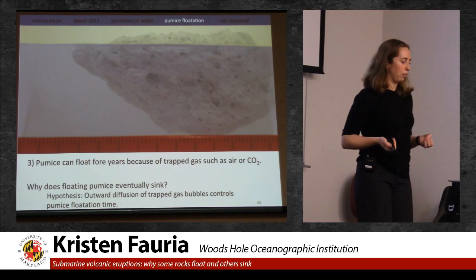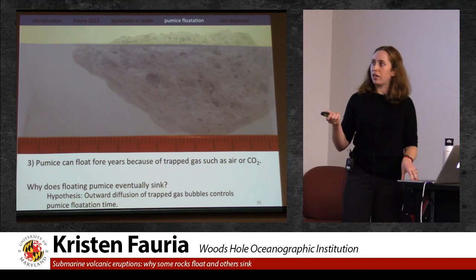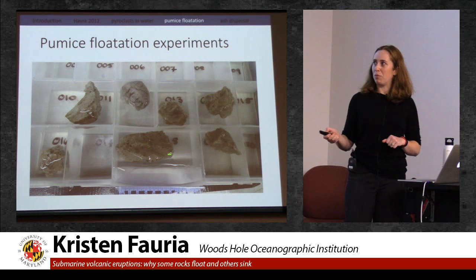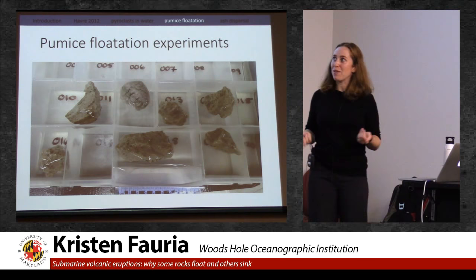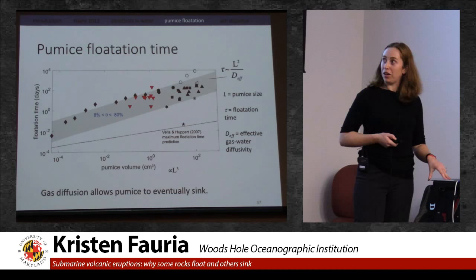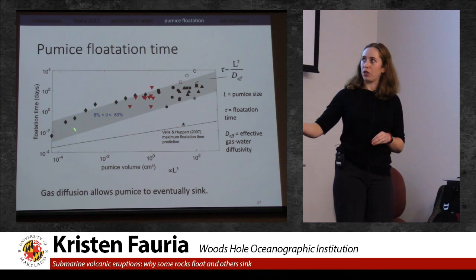And so in order to test this idea, we conducted very complicated pumice flotation experiments. We put pumice on water and waited until they sank and measured the total amount of time they stayed afloat. And so I'll show you our results here. So this is pumice size. This is the volume versus the total flotation time. We had to be a little bit patient.